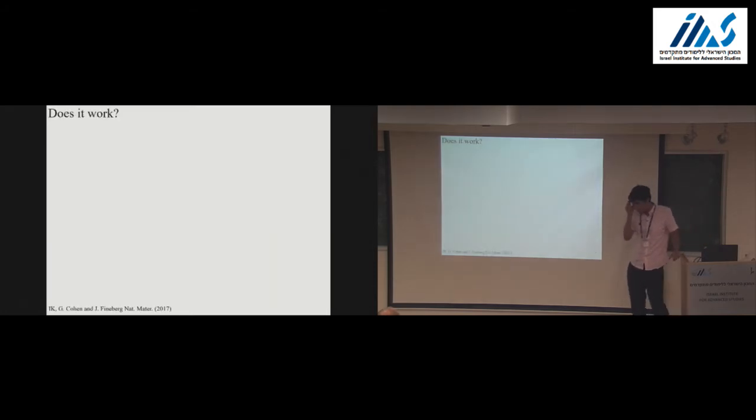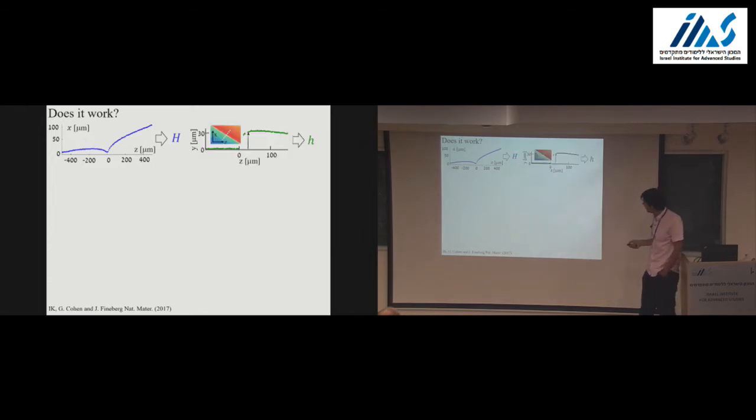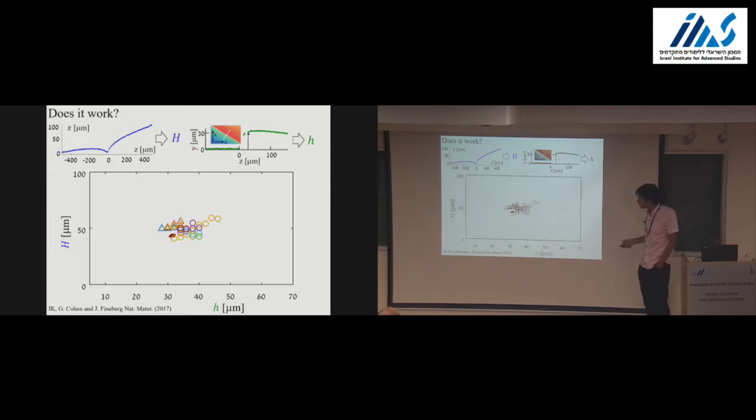So does this picture apply for our case? We take crack fronts and compute the predicted added area, and we can also directly measure the step height. And here we see that for a range of steady state steps we get more or less the same value.